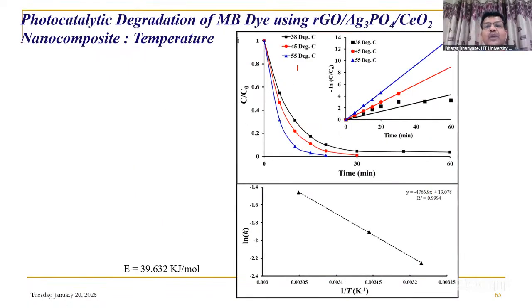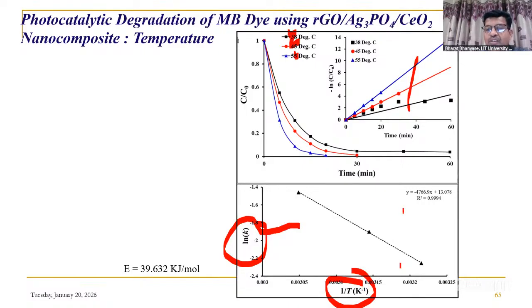We have carried out this degradation at different temperatures, that is 38, 45, and 55 degrees. From that, rate constant was calculated by fitting first order kinetics. Then we applied the Arrhenius temperature dependence, that is K equal to K0 e raised to minus E by RT. From that, the ln K versus 1 by T plot was done, and from that we calculated the activation energy, that is 39.63 kilojoule per mole.